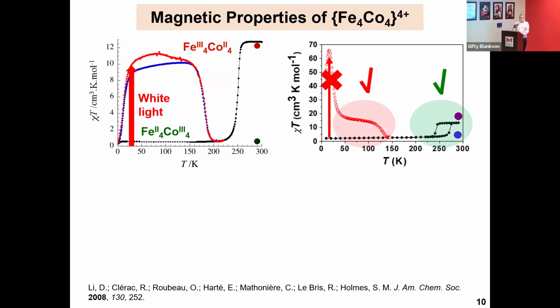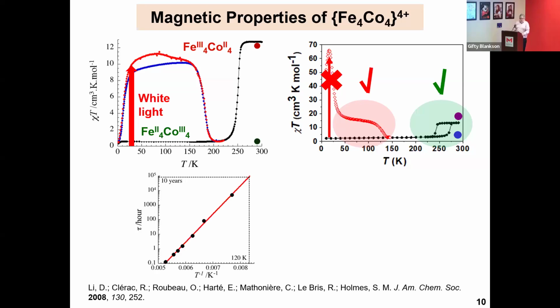Now we don't see this thermal hysteresis in the magnetic measurements. It's because the molecules really aren't cooperatively talking to each other, this contraction and expansion. It's about 2 Kelvin. We determined that through other experiments. But this is the first time we've been able to mimic all the salient features of the three-dimensional Prussian blue. And there's the Arrhenius data showing the thermally trapped relaxation. That is relaxation as you increase the temperature, or you follow the optically trapped data with respect to time. It's superimposable. It follows Arrhenius kinetics, so there's got to be some thermally activated state.